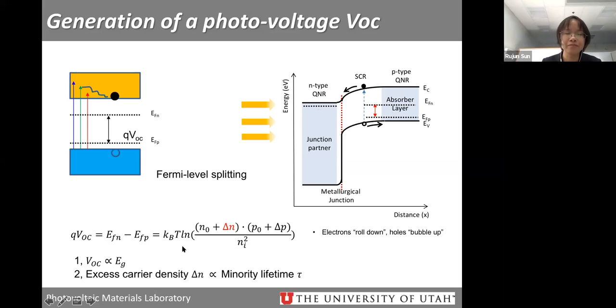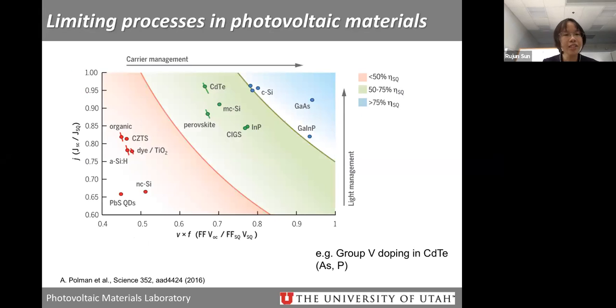So the VOC we can get is first proportional to the band gap: higher band gap, higher VOC. But for the same material, the quasi-Fermi level splitting will be reflected by the excess carrier density, or we can call it the minority carrier lifetime. This can be measured and reflects the processes happening in our solar cell. So this map tells us the potential we can reach.